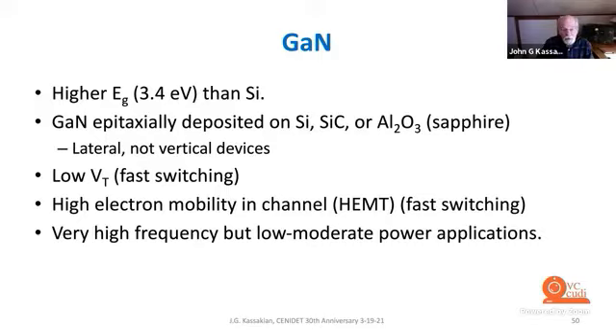They have a low threshold voltage, so you can switch them quite fast. The electron mobility in the channel at the interface between the aluminum gallium nitride and the gallium nitride results in what's known as a high electron mobility transistor, which also enhances the switching frequency. So gallium nitride devices are used at very high frequencies, but at low to moderate power applications. In those applications that can afford the additional cost of gallium nitride, the device has substantial advantages. But again, it is an expensive device.